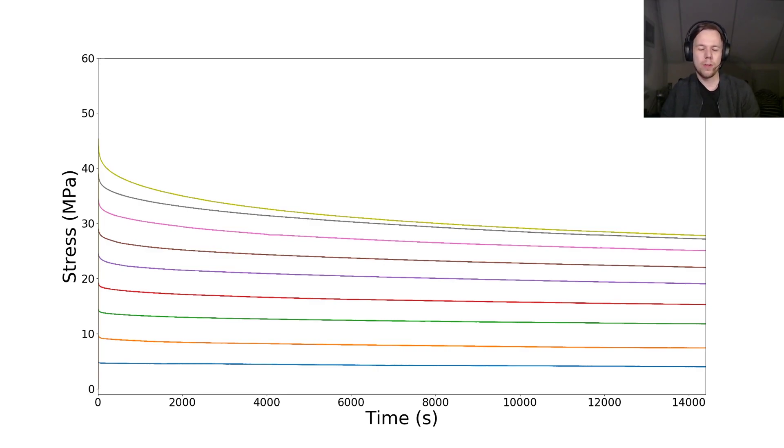What we start out with is simply the initial forces, the initial stresses rather, of 5 to 45 MPa. And what we see here is nice. It's quite regular. There's no strange things happening. And there are two things really that stand out to me. One is that every test appears to start with an exponential decay, and as time goes on, that eventually turns into a linear decay.